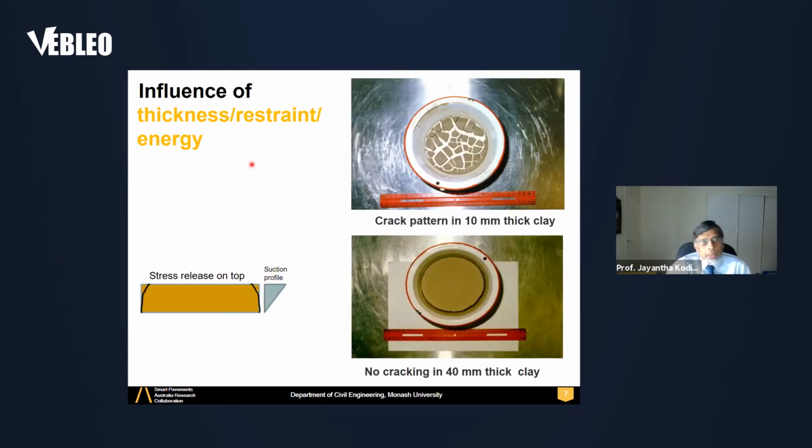Influence of thickness and restraint and energy. On these pictures, you see two clay layers drying on the laboratory bench. The first one is a 10 millimeter thick layer. It has cracked severely, and the same soil placed in a 40 millimeter thick layer in the same size container has undergone